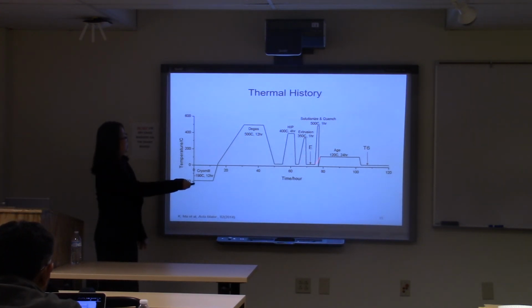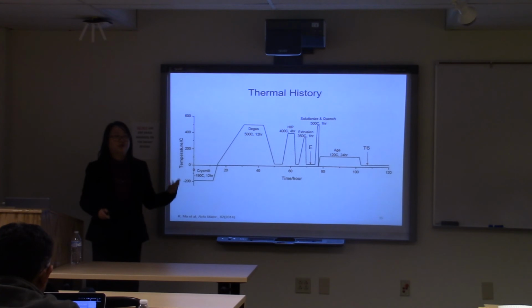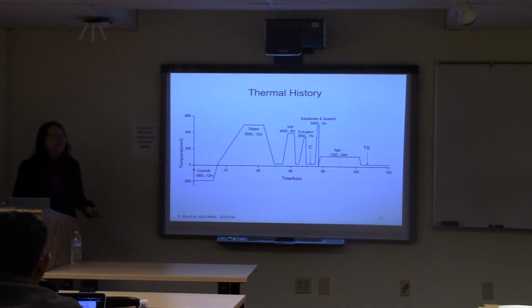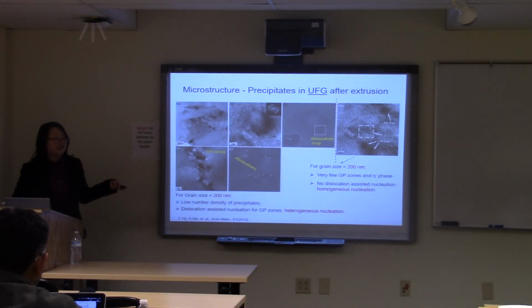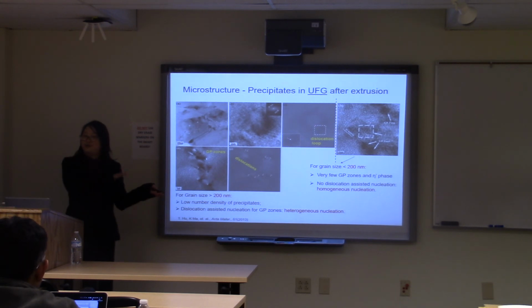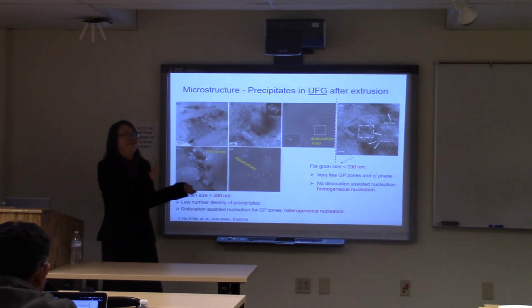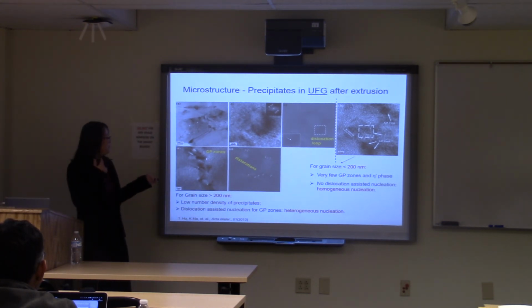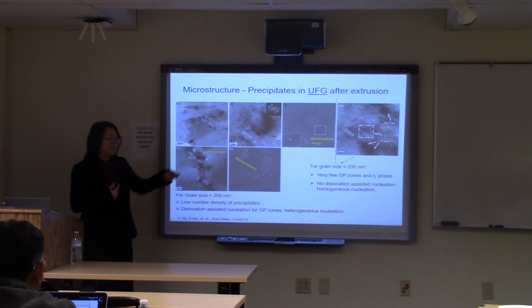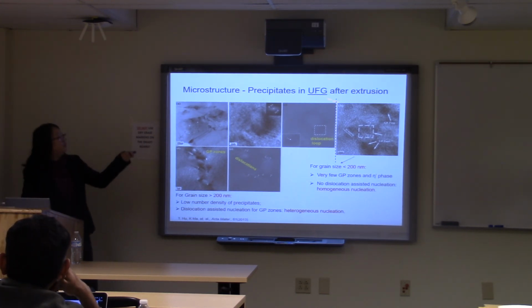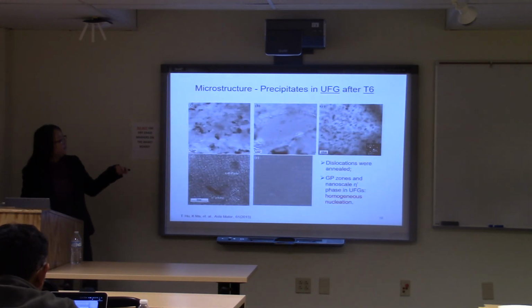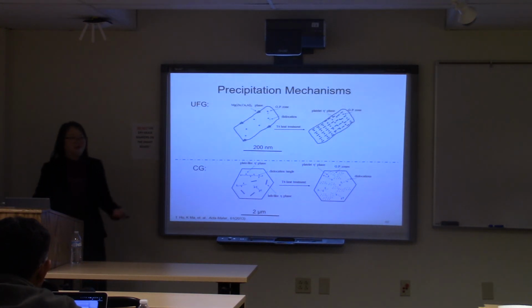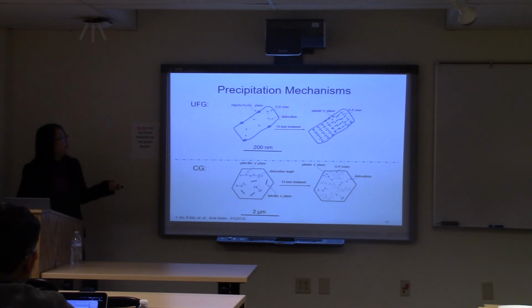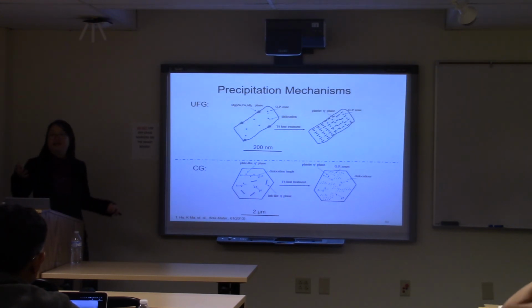That's where I first look at the microstructure in the extruded condition and then after the T6. Just to remind you, T6 is the processing that brings you those precipitation strengthening here. I'm going to skip a couple of TEM images, but I want you to get a sense that it's really a lot of work to get those TEM samples. What we focus on is looking at the grain size, the precipitates, and the dislocations. Each slide corresponds to different materials in different conditions. But I do have a schematic which I would like to stop here to explain what happened, from what we observed from TEM. On the top is the ultrafine grain material made from the cryomilled powder. On the bottom is the coarse grain material.